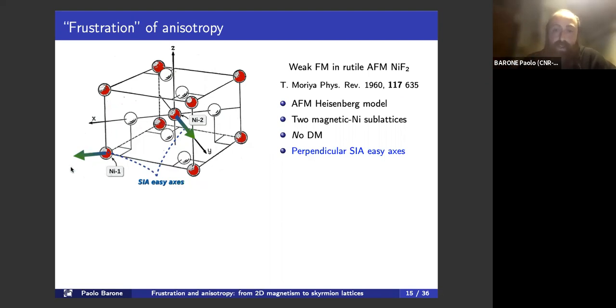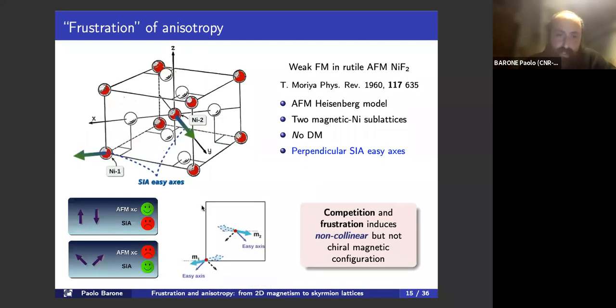Now the point is that there are two magnetic sublattices with perpendicular single ion anisotropy axes. And this, of course, brings in a competition again, because now, because of this perpendicular easy axis, the spins also want to be perpendicular to one another, and this competes with the isotropic exchange that wants them to be parallel. So in the end, the ground state or the long range order in this system is a canted antiferromagnet, where the two magnetic sublattices start from being completely antiparallel, and then in order to optimize the magnetic anisotropy energy, they cant a bit. And so this is a non-collinear phase induced by the frustration of anisotropy, but it's not chiral.